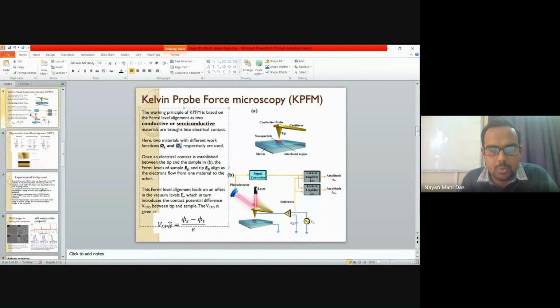So it's the equation that is used to calculate this contact potential difference. This is the VCPD, which is the work function of the surface minus the work function of the tip divided by the electron charge. For our case, we keep this electron charge as 1.